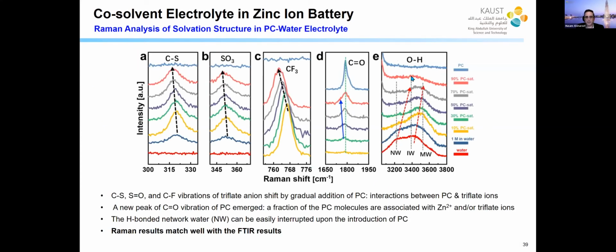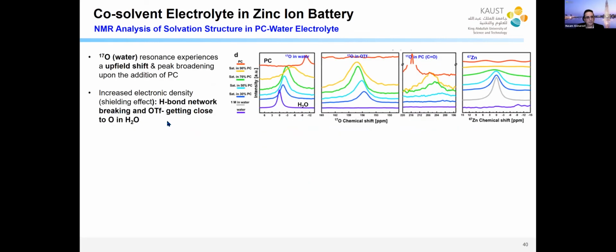You can do this also with Raman. These are a series of Raman spectra for the same thing, looking at CF3 and SO3, and they all show peaks developing from nothing as you add this PC, and shifting. So clearly, all this data collectively shows that this anion is interacting with the PC. And we also did some NMR. You look at the oxygen-17 in the water, and you see that as you add PC to the water, there's an upfield shift.